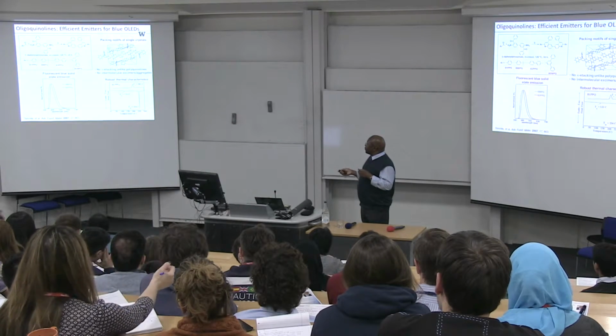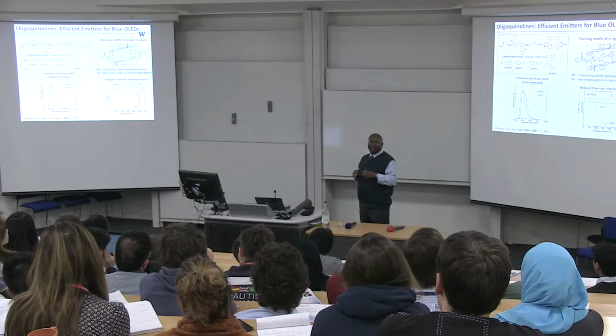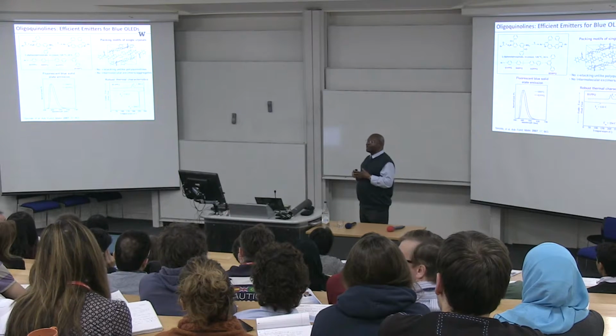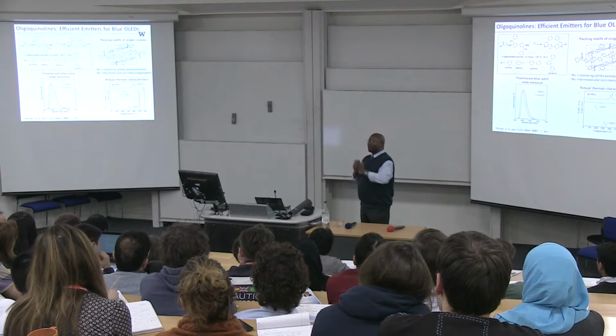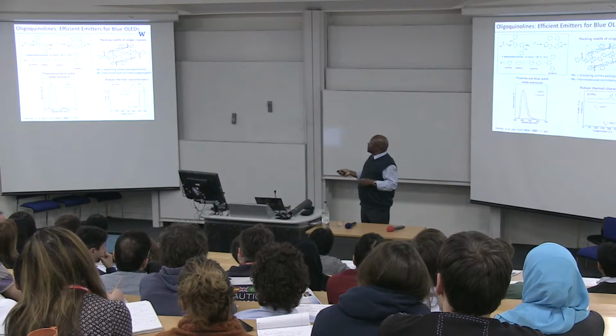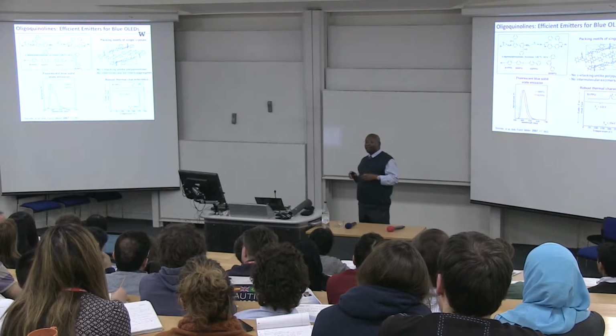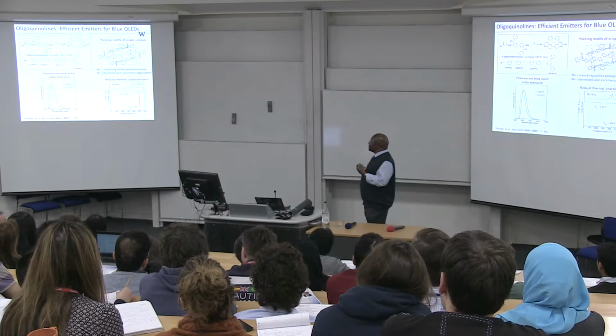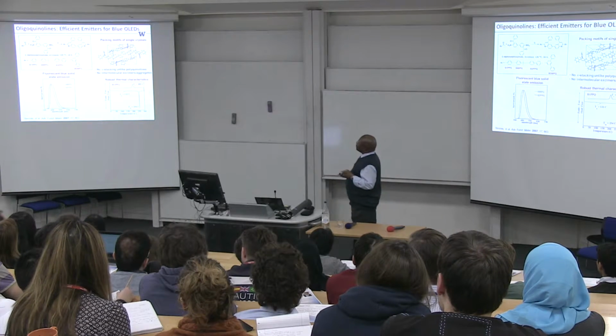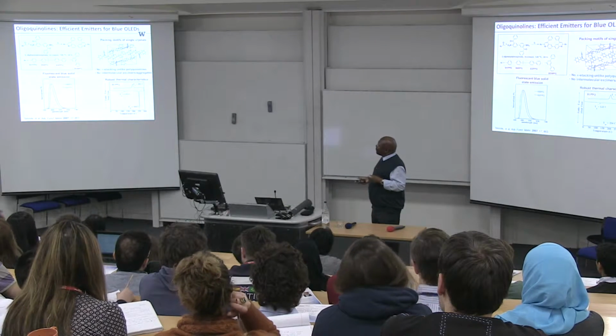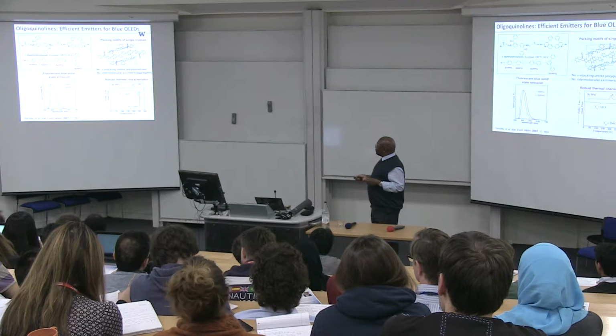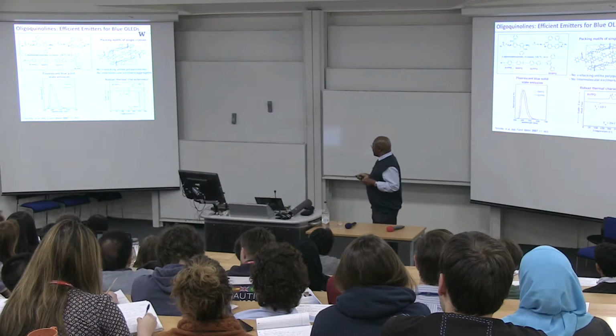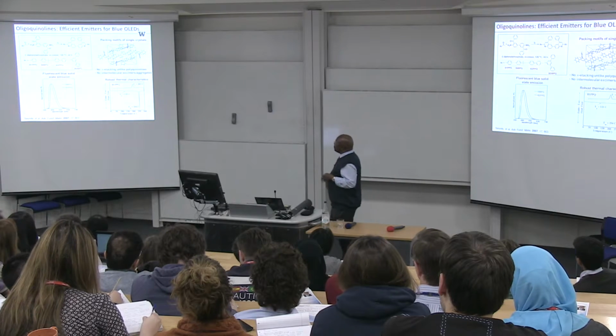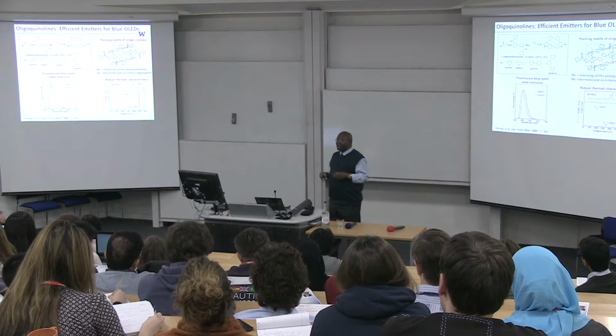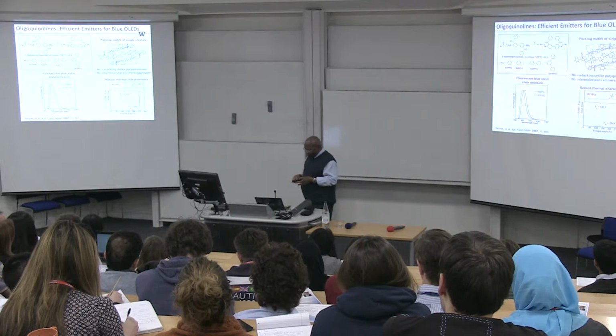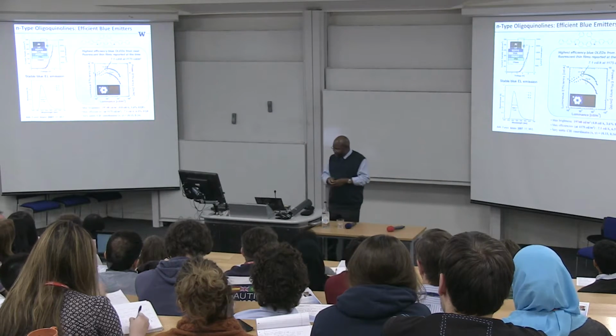And we were able to show that even when they crystallize, they did not pi stack. They did not form a structure that pi stacks. And the reason for that is because of the side chains that are attached to the backbone. So that prevented the ability of the molecules to pack efficiently, and hence you can retain very efficient blue. And furthermore, as you can see from here, the glass transition temperature is quite high, which means that they are robust and can be used very well in OLED devices.